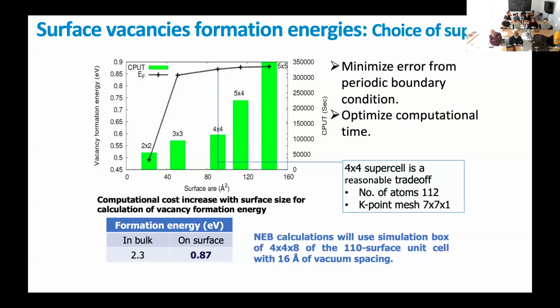So you will see that the vacancy formation energy is really affected by that. And the CPU time is also really increasing tremendously in this case. So you need to find a compromise, which in this case is that the 4x4 supercell is the reasonable trade-off. And we are dealing with an ab initio slab, which has 112 atoms. This is the K-point mesh that we use. And yes, we're using GGA, PBE GGA.